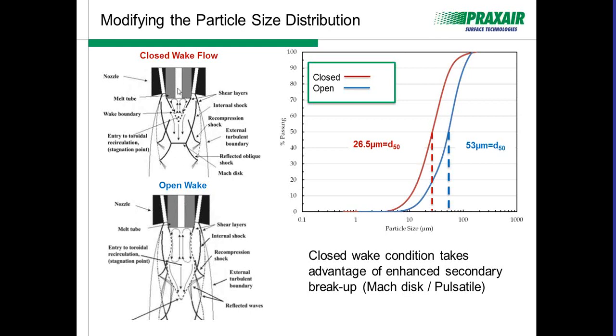And so as the liquid falls out of this nozzle, it's going to be either pushed or pulled out of that nozzle depending on this gas structure. As it's pulled out of this nozzle by a type of aspiration or vacuum that's created on the tip, liquid will fall. As it strikes this Mach disk and breaks it up, this high pressure zone is released into what we call the shock bottle.